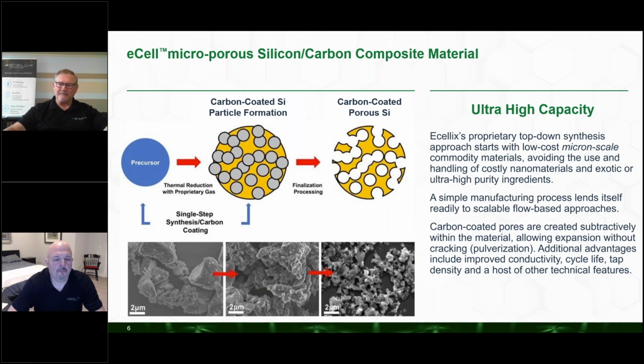So we have these two problems. One is that we're expanding and contracting, causing cracking. And as we crack, we're exposing more surface area of the battery, which leads to reactions in the battery, which actually hurt the battery and cause it not to last very long. So we're looking for technologies that enable us to build batteries that can expand and contract, and at the same time manage the surface area so we don't get harmful internal reactions.